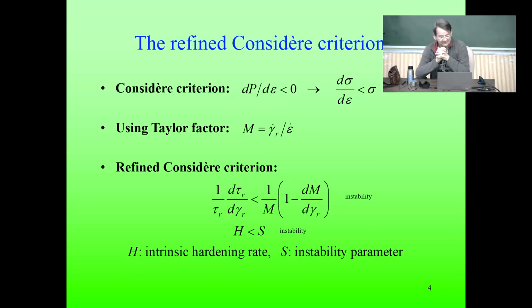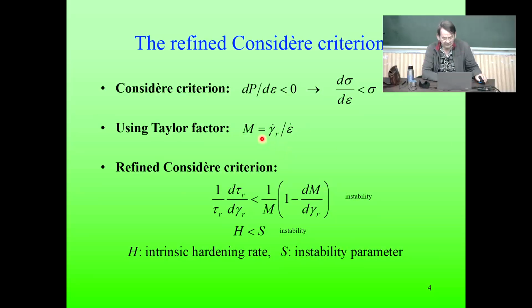Taylor factor. So Taylor factor, the M value, is simply... The Taylor factor is the ratio of the slips, all the crystallographic slips within the crystal divided by the macroscopic strain rate. It can be single slip or can be multiple slip. So if we use this, you see the gamma dot R and epsilon dot and epsilon, they are related. You can put it in, and you can rewrite this instability criterion into this formula.